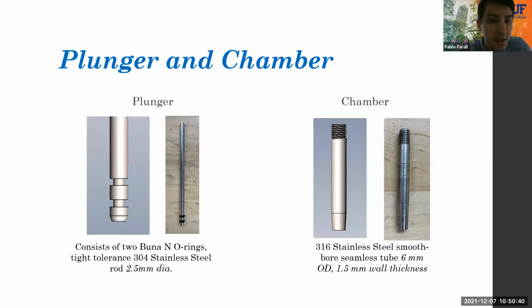So the plunger and chamber subsystem is responsible for drawing in and ejecting liquid. It consists of a sliding plunger with 2 O-rings that fits tightly inside the cylindrical chamber. As the plunger moves up and down the chamber, it creates the necessary pressure difference to draw the liquid in or eject it. Both the plunger and the chamber are made out of stainless steel due to its corrosion resistance, cleanability, and strength. And we decided to go for off-the-shelf parts for these 2 parts because we wanted to reduce any possibility of surface imperfections that could affect the seal created by the O-rings.